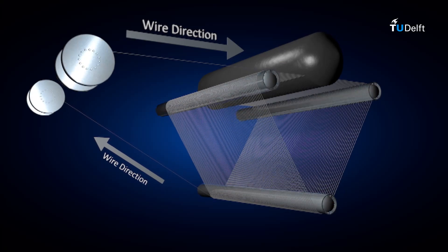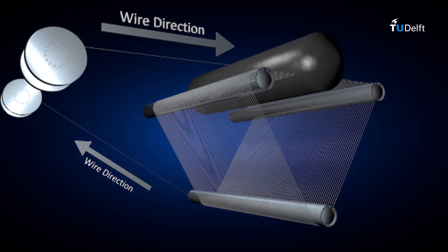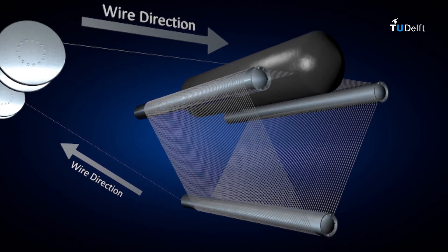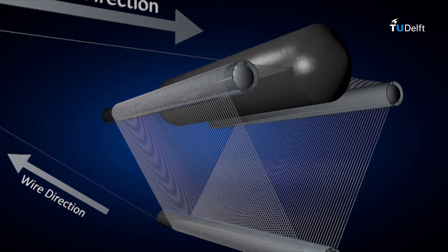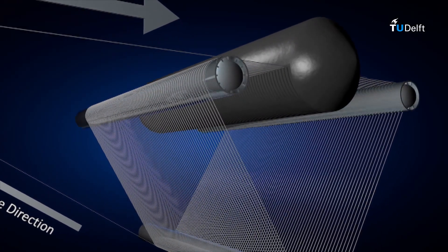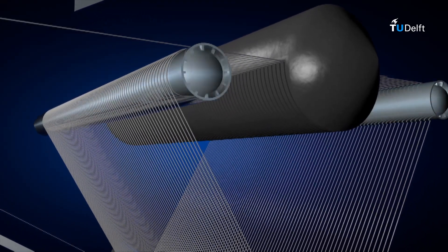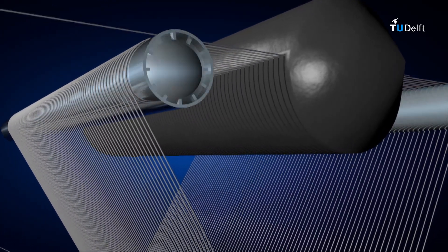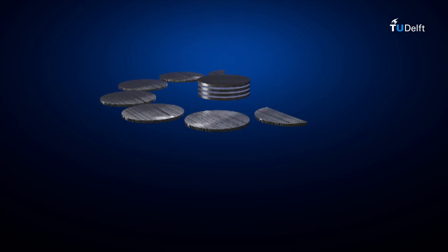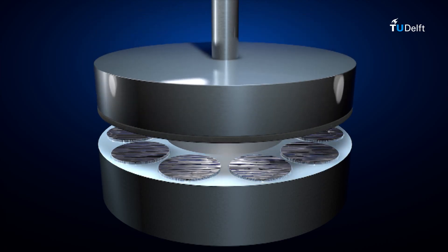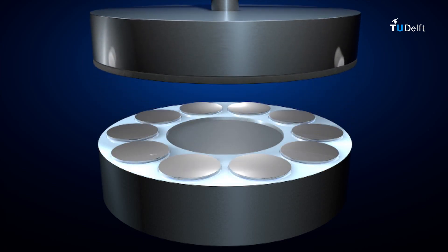A disadvantage of the sawing step is that we waste a significant fraction of the silicon as a kerf loss. The kerf loss is usually determined by the thickness of the wire or saw used for sawing, and is in the order of 100 microns of silicon. This is a large fraction of the ingot if we consider that typical crystalline silicon wafers used in solar cells nowadays are in the order of 150 up to 200 microns. Sawing will logically damage the surface of the wafers, so this processing step is followed by a polishing step.